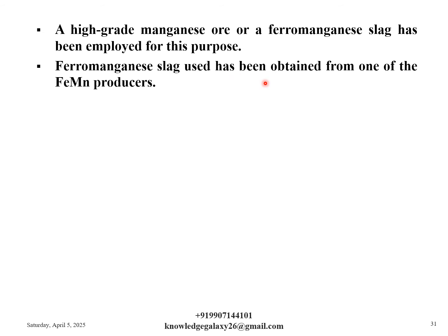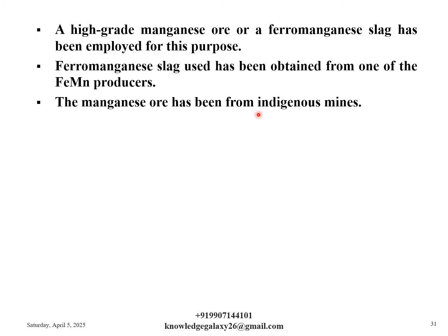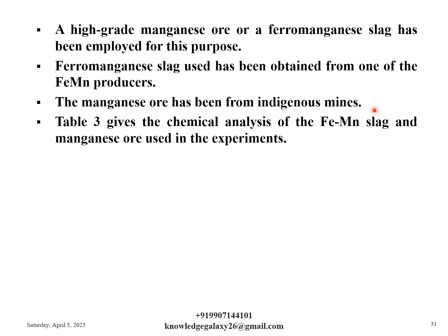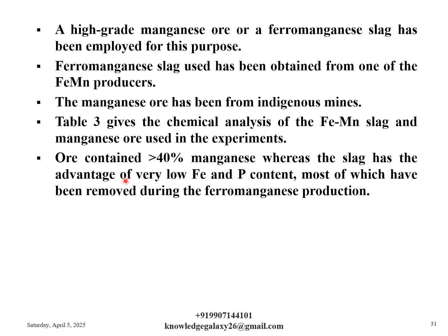Ferromanganese slag used has been obtained from one of the ferromanganese producers. The manganese ore has been from indigenous mines. Table 3, which is given in the next slide, gives the chemical analysis of the ferromanganese slag and manganese ore used in the experiments. Ore contained more than 40% manganese, whereas the slag has the advantage of very low iron and phosphorus content, most of which have been removed during the ferromanganese production.